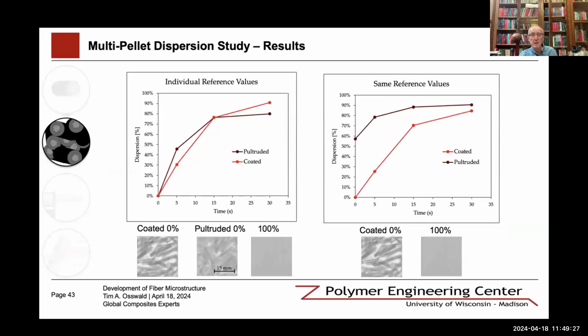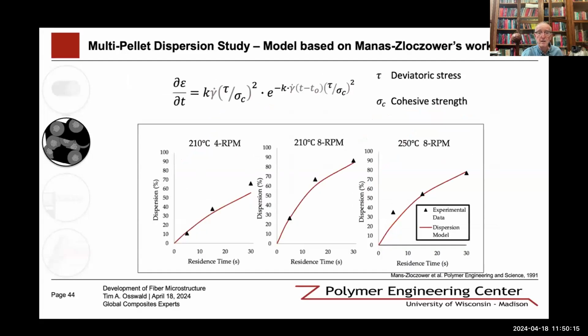So here you can see, for example, individual values. So the dispersion, the pultrusion versus the coated on the right-hand side, is using the same reference value. For example, the pultruded ones already have a certain dispersion within them. So they start out, if you compare them one to one together, with a certain dispersion as compared to the coated values. So what we do is we normalize it and use individual reference values for pultruded and coated as 0% dispersion. And so that's the left-hand picture, by normalizing it to their initial dispersion value. So those are the measured values.